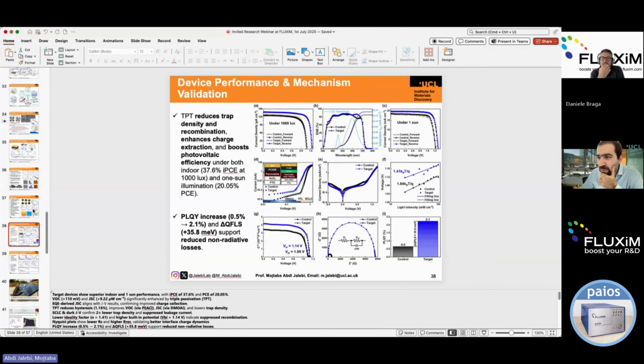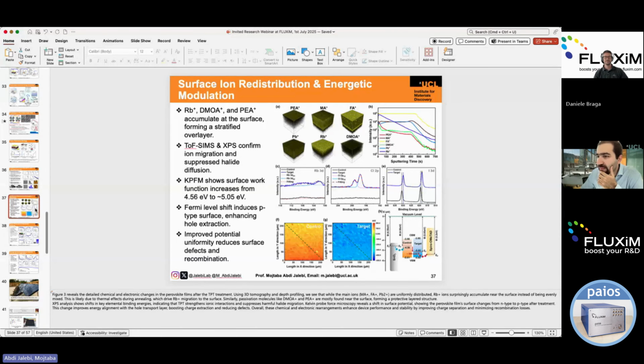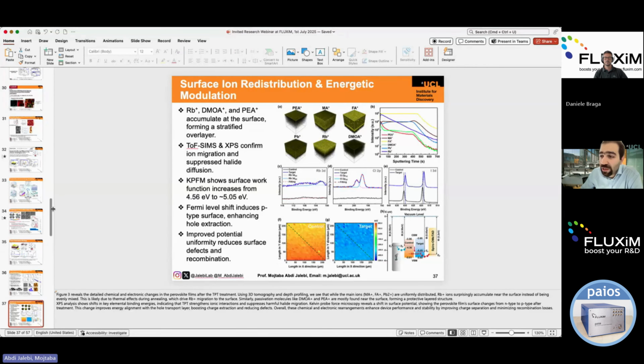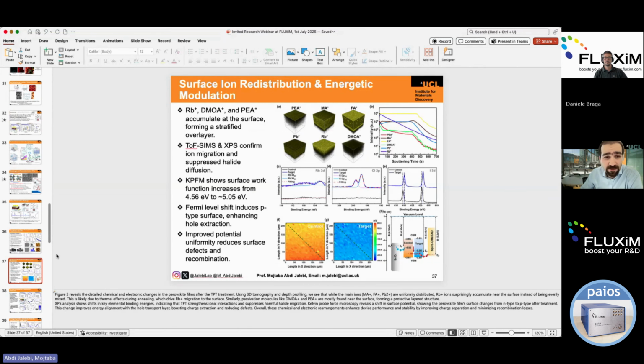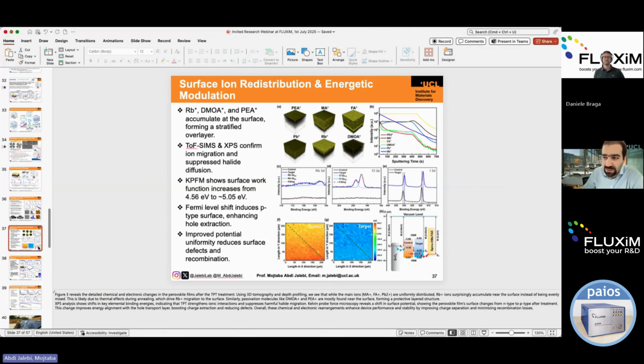I haven't shown the data for that, but yes. DMAI helps us release the strain in the perovskite crystal structure. We have done a measurement, but unfortunately I didn't put it here because of the time limitation. It helps us release the strain within the perovskite structure based on our GIXRD. We are not the first to use DMAI. It was used for the first time in Michael Gratzel's lab by Dr. Lucas, who tried DMAI in perovskite, also at the interface, and found that DMAI can help release the strain and give a better crystal structure within the perovskite. So the short answer is yes.